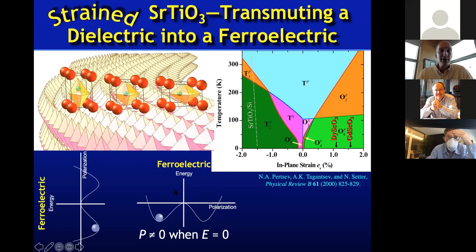If we look at what happens with biaxial compression, it again corresponds to the cartoon that I have, where the coordination polyhedron, the octahedron around the titanium, has elongated in the out of plane direction. So now the titanium can rattle up and down in this same double well. And it breaks symmetry, it goes off center, and that gives rise to a polarization now that is either up or down. So it's a different phase, and that's why it's indicated here by this phase, as opposed to that phase. It has different symmetry. This one's tetragonal, this one's orthorhombic. But you can see that the effect that was predicted on strontium titanate is huge in theory.